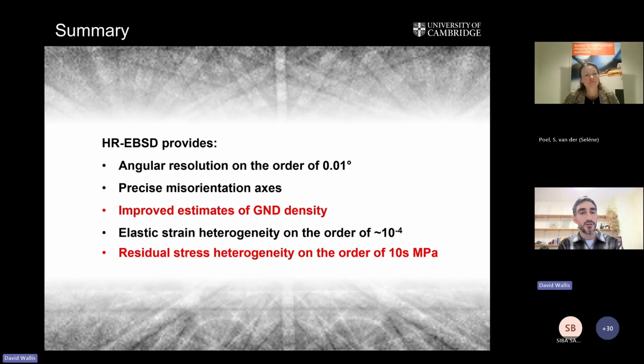Yeah, no, there's definitely a lot of things we need to think about. One of the most practical ones is you need a really good surface polish on the sample, much better than even for normal EBSD. This technique's so sensitive that if you have any remaining really subtle scratches in the surface, they really stand out like a sore thumb in the results. So you need to put really careful thought into how to polish and prepare the sample surface very cleanly.